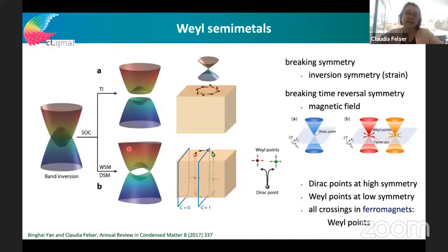So the crystal is now a semi-metal because we still have electron density between the occupied and the unoccupied states. So we have a different electronic transport. It's not an insulator. And therefore, these are the bulk properties. And due to these bulk properties, we can also have a surface state which has a very special spin structure. So as I said, we can distinguish between Dirac and Weyl points.